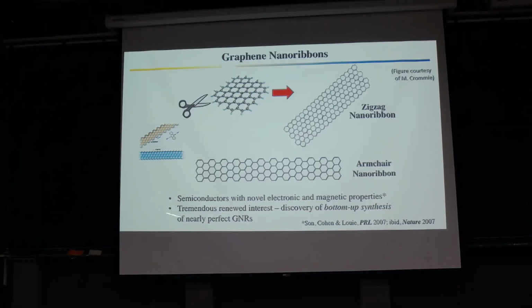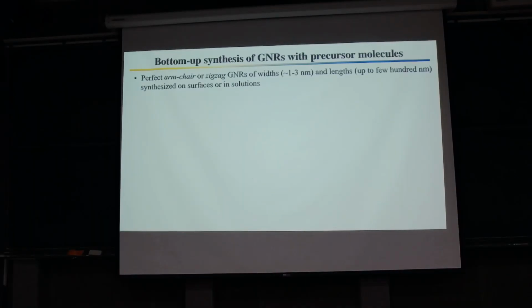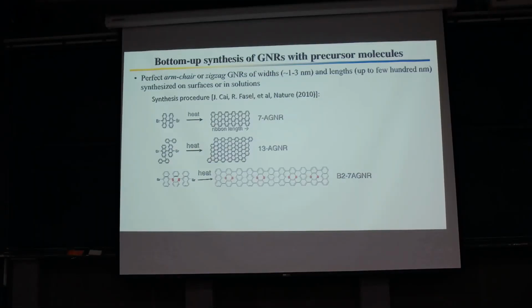However, nowadays, there is really tremendous renewed interest in the graphene nanoribbons because our clever experimental colleagues were able to discover a way to synthesize nearly perfect graphene nanoribbons. And so nowadays, you could get armchair or zigzag or other types of graphene nanoribbon with a width of about 1 to 3 nanometers and length up to several 100 nanometers. And those are synthesized by taking precursor molecules and putting them either in a solution or on top of a metal surface. And you just heat it up, of course, under the right conditions. The molecules will polymerize and you will get perfect graphene nanoribbons.